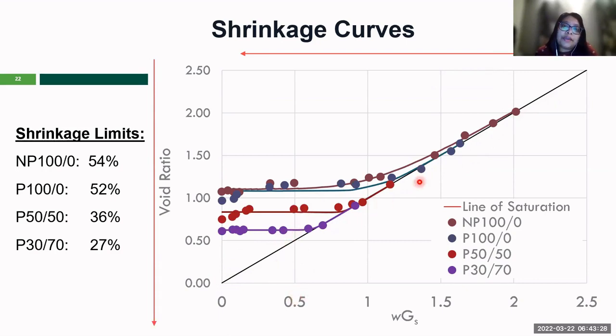So air enters when the deviation happens from the line of saturation. And if we just look into this red line here, which shows the shrinkage limit, the intersect of the stable volume and the line of saturation. So these are where we have the stable volume and they intersect with the line of saturation for this material.